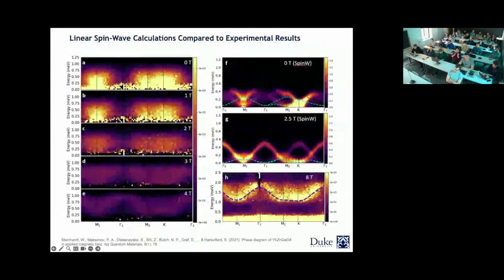What we also have done with regard to this 1114 compound was that we made the compound, so this previous one was with magnesium, then we made it with zinc. The reason we decided to look at zinc is that if you think about zinc 2+ and gallium 3+, they have the same electronic configuration. So if there is, well, not if, we know that there is site mixing. So what happens if you try to suppress the electrical fluctuations by picking two compounds that are closely related to each other? That is what we have done.